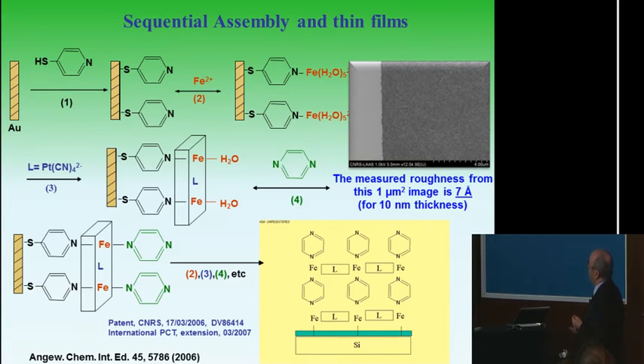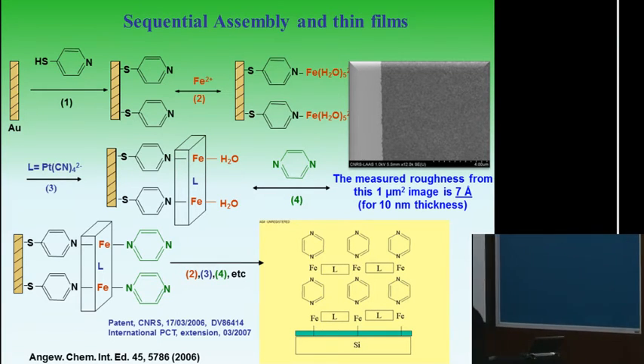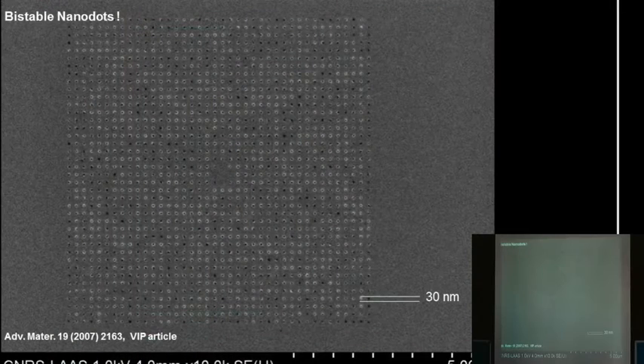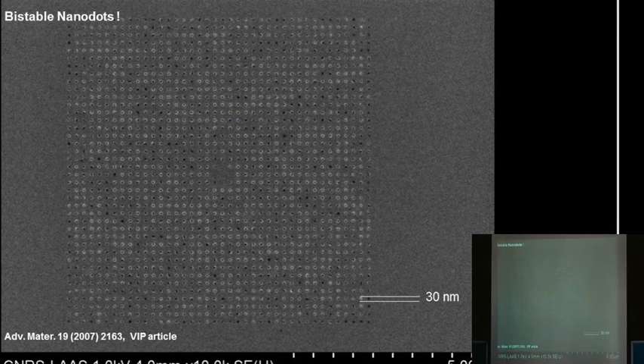So then that means that today we have our thin films, and of course what we wanted to do, to use e-beam lithography, because we have in Toulouse a nanotechnology platform, and then we used a combination between layer by layer synthesis technique with e-beam lithography in order to have something like that. So then you have nanostructurations, you have dots, okay? It's the surface which is nanostructured. You have 30 nanometers for each dot here, okay? And then you have a very well organized surface, and each dot is a spin crossover dot with maybe hysteresis.